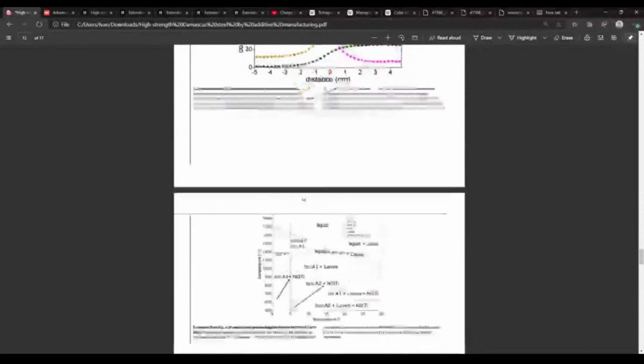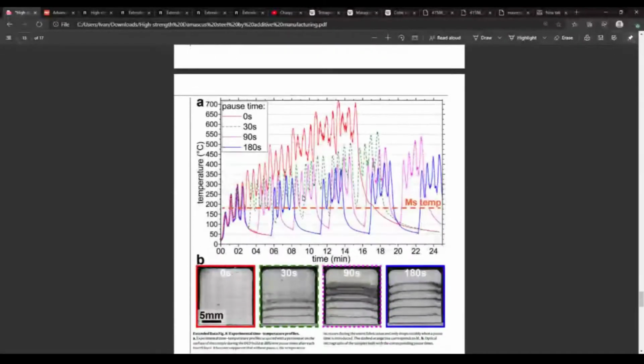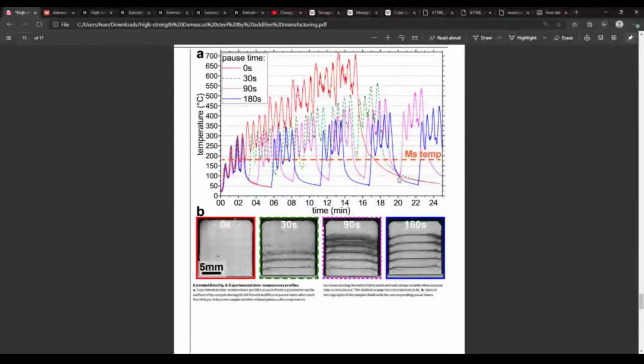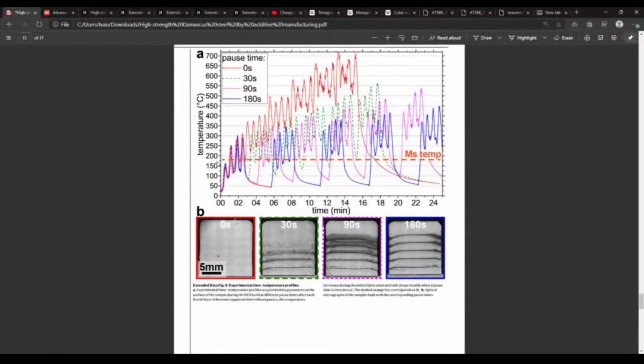All right. So this graph pretty much tells the whole story. Different plots show the rising of temperature, which they measured by pyrometer, and as they're laying 4 layers and then waiting, we can see the 4 peaks as the 4 layers were laid, and then they shut off the machine.